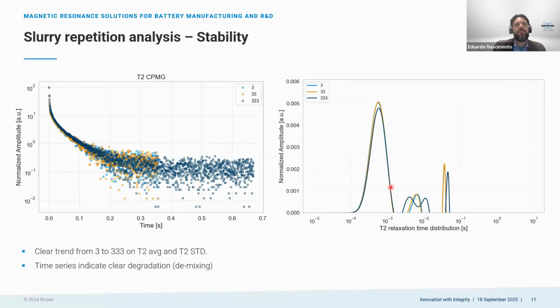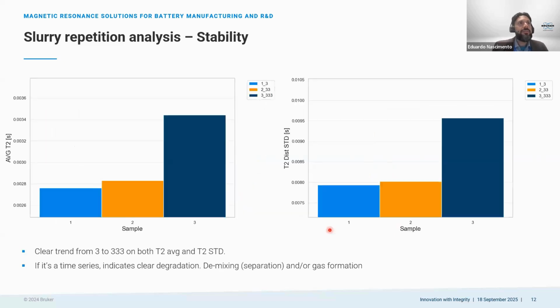So you can see for the very first 2 measurements, for the color blind people, the blue and the orange spectra here are overlapped. But for the last one, which was measured at the end of the day, this peak here starts to separate, and even the peak on the right starts to shift to the right. And this is a clear indication that something was going on. So another way to analyze the same data is that you can transform that graphic into a number, like calculating the average T2, or even the distribution standard deviation. And again, you can see that for the very first 2 samples, the numbers are quite comparable, but for the last one, the sample was already demixed.